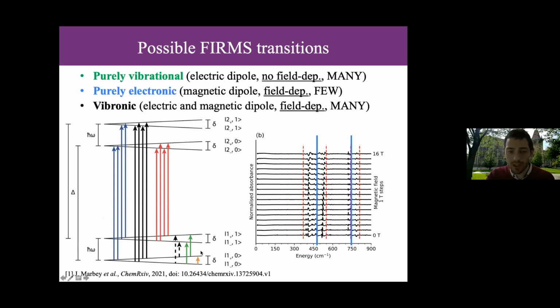So this is our ground crystal field state with an extra vibration, and this is our excited crystal field state with a vibration. And so the purely electronic lines are these blue ones, and the EPR transition is also a purely electronic one that I show here, but we're far too high energy to see that. That's of course in the microwave regime, not IR.